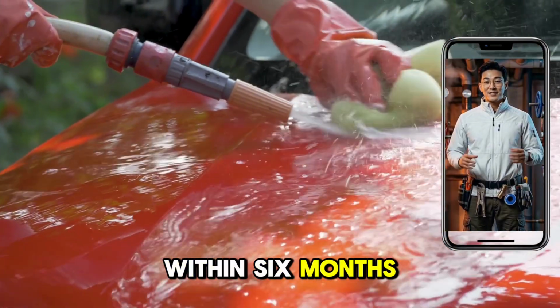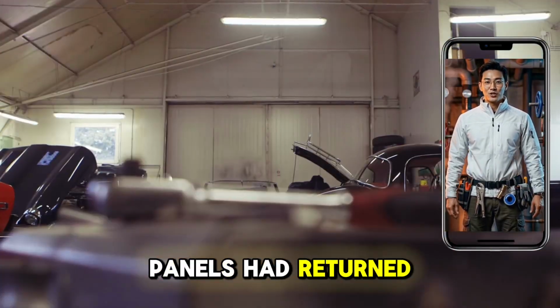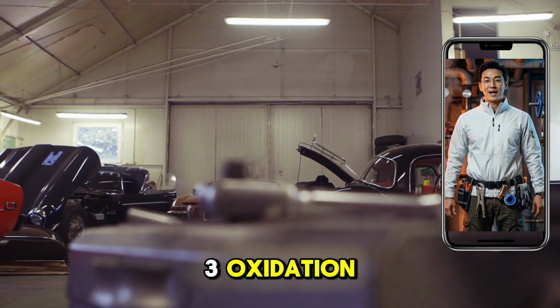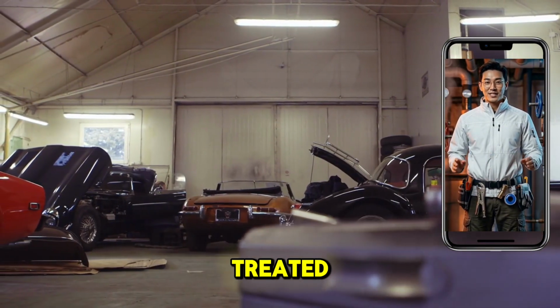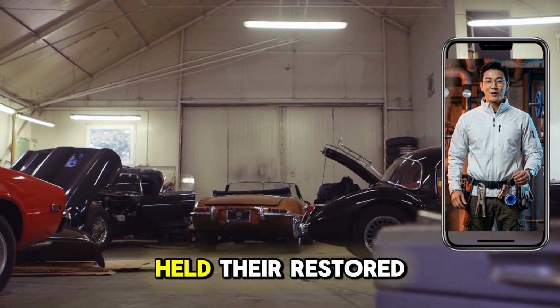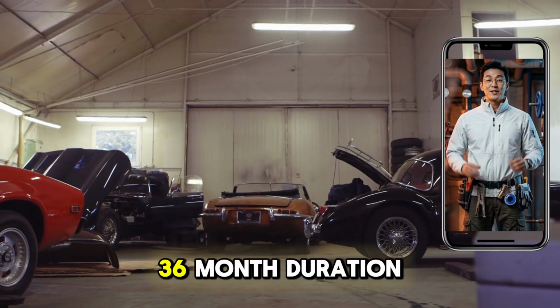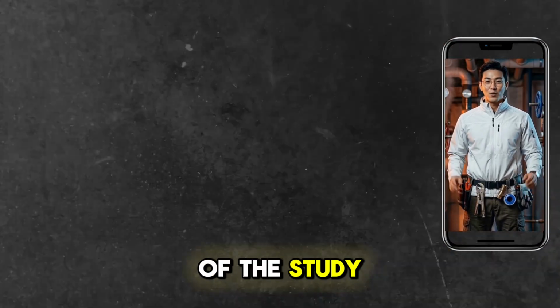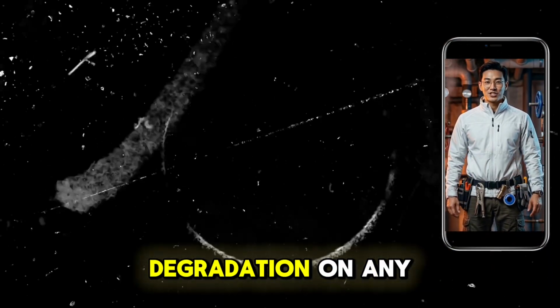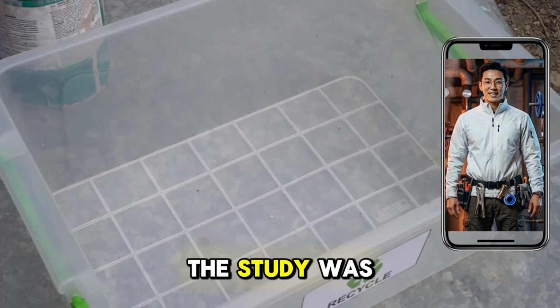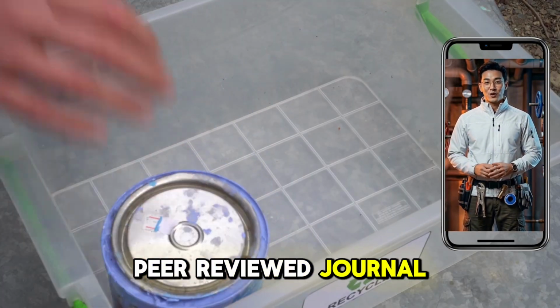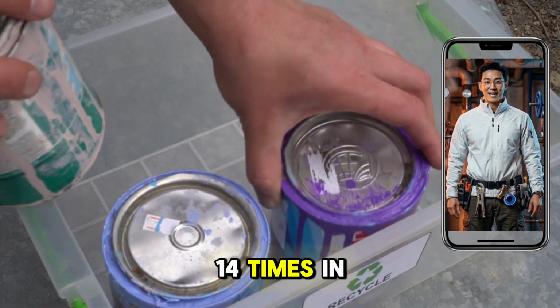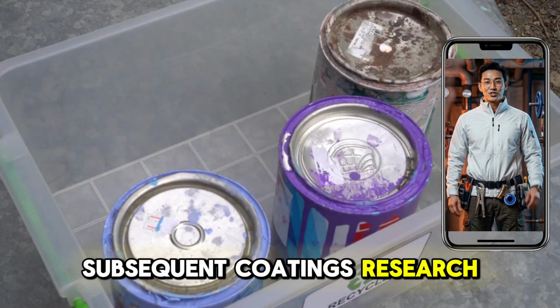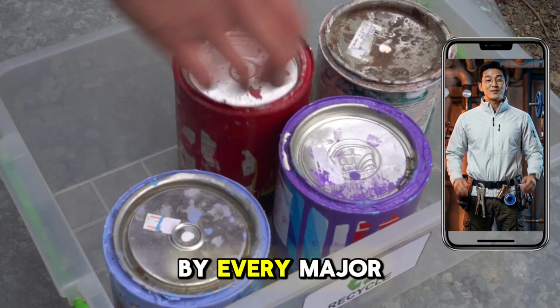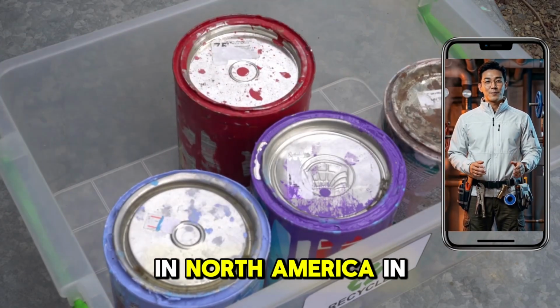Within 6 months, the rubbing compound panels had returned completely to Stage 3 oxidation as if they had never been treated. The resin-treated panels held their restored finish for the complete 36-month duration of the study, with 0 measurable degradation on any panel. The study was published in a peer-reviewed journal. It was cited 14 times in subsequent coatings research. It was completely ignored by every major auto body chain in North America.